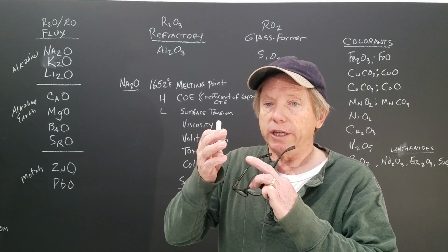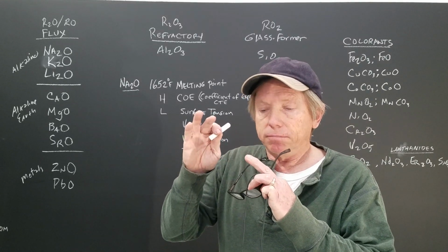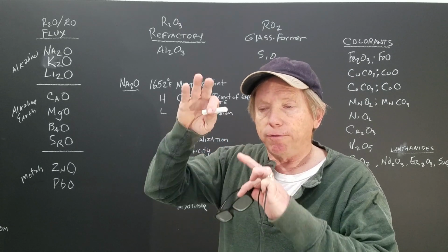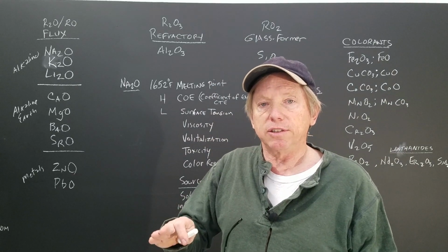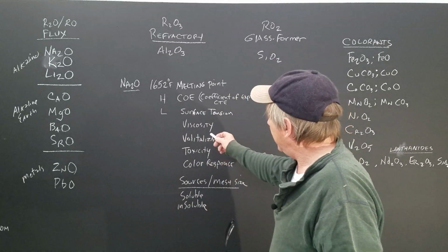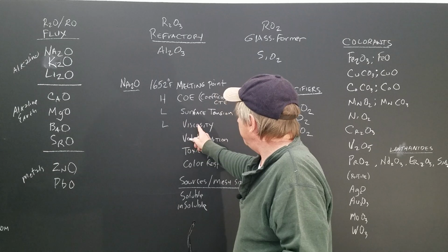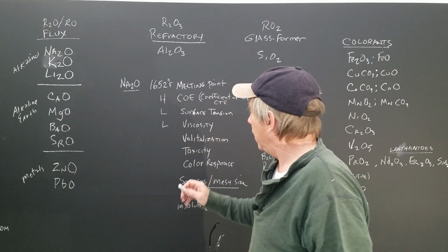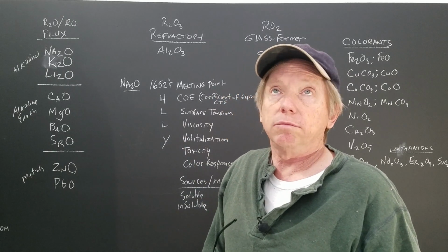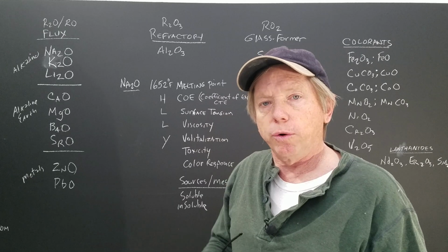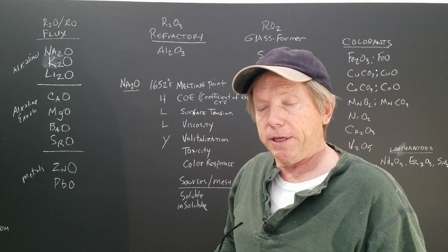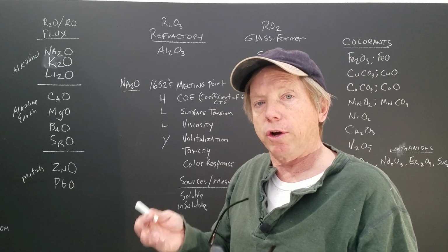Because if it gets on your glaze and there's any irregularities or discrepancies in the coat, then instead of flowing over it and healing itself, it'll bead up into crawl spots. Okay? It has a low viscosity. Viscosity is thickness, like honey. It does volatilize. It goes off as a gas at about 2012 or something, and that's how we do soda firing and salt firing, because of the property of sodium going off as a gas.